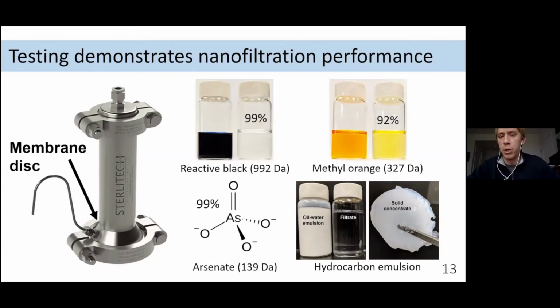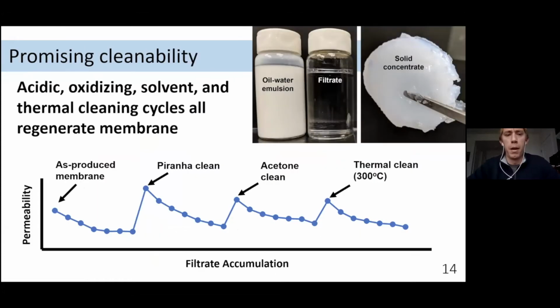One major issue with polymeric membranes, specifically with oil-water emulsions, which are quite common industrially in a lot of different spaces, is that the oil readily fouls the polymer membrane surface and then blocks the flux of water relatively quickly across that membrane. What you'd really like is to do this without any fouling or with minimal fouling, or at least cleanability once fouling does occur. So we have done a lot of different cleaning studies with the membrane. We've used really heavily loaded oil-water emulsions, as you can see in the top right.